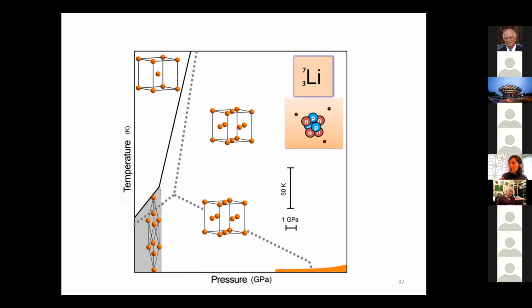Okay, we did two things. The second thing I'm going to hold for the next part. That is, we looked at the electronic structure of lithium, but we keep it for later. The one thing we did is this: we know that if we cool down, we always land from FCC, BCC to 9R. We also know that if we pressurize, we go from 9R to FCC. So that was the path everybody took, and everybody thought that this experimentally confirmed that this is the ground state. What if, theoretically, FCC was the ground state?